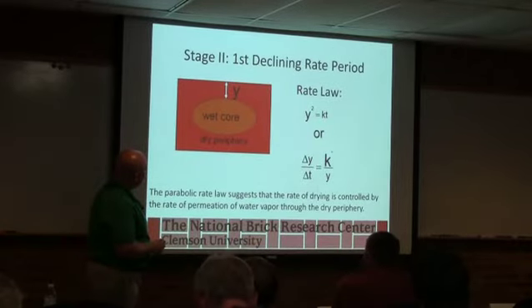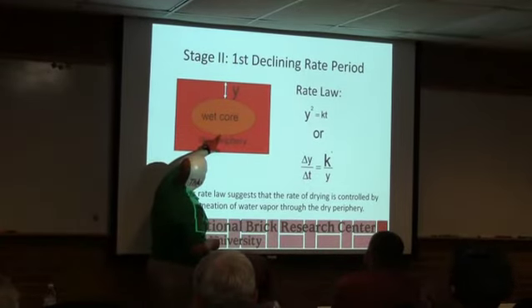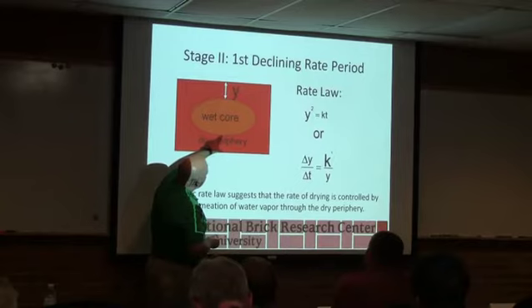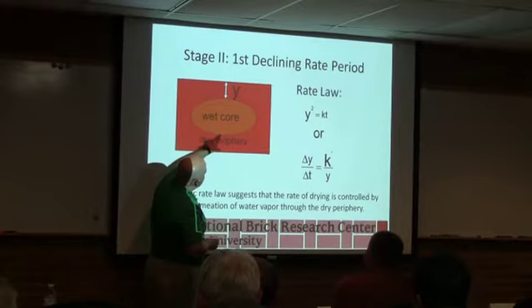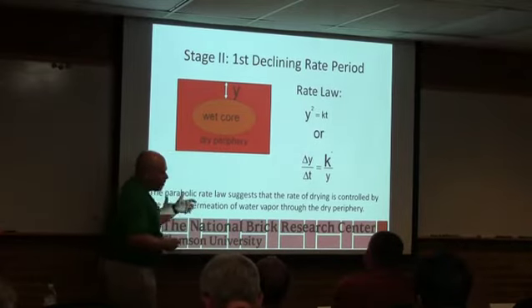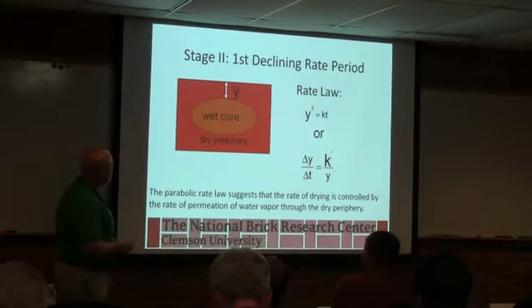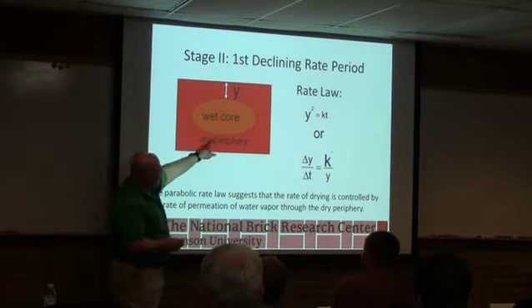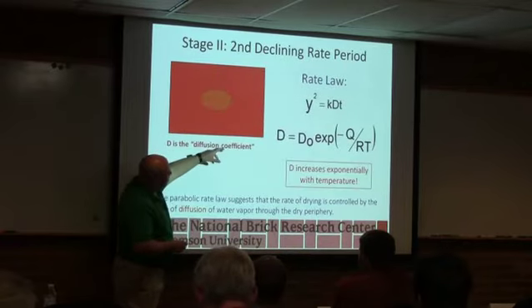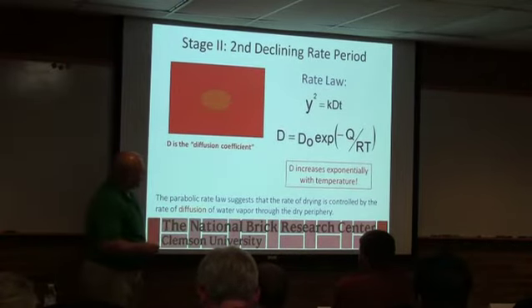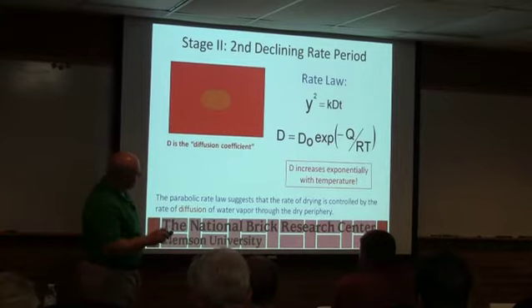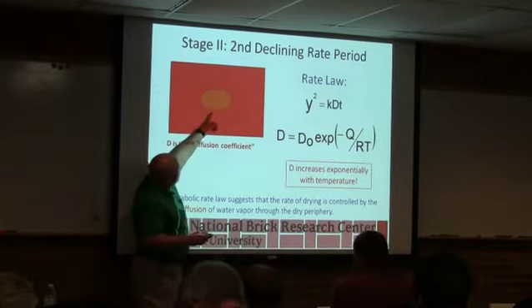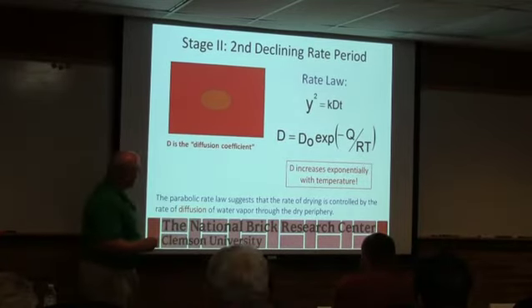All right. So when you're in those declining rate periods, basically the thickness of this dry skin that you've got to move water through becomes important. And this is starting to get a little too much math in it. But you talk about a shrinking unreacted core model. You can do all kinds of math if you were interested in it. But it basically becomes progressively harder and harder. And this thing is saying the same thing. So we're predominantly using temperature when we get toward the end of the drying cycle to force the water out of the interior and through that shell without causing any damage.